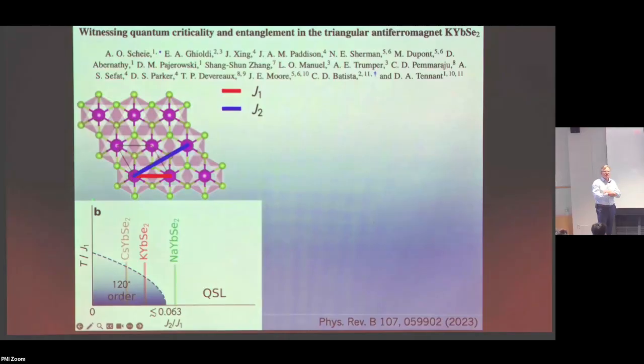All right, now the materials that people have been looking at are these delafossite-type systems, and so here's one of them, with this kind of crystal structure. This is the rare earth ion, which is six-fold coordinated by selenium, and potassium is part of keeping these things apart. You can change the alkali site, and as you change it, it seems that you're changing the ratio between J2 and J1. The thing that Steve White did to scan with his DMRG across this system corresponds to adding in different alkali elements to the system.